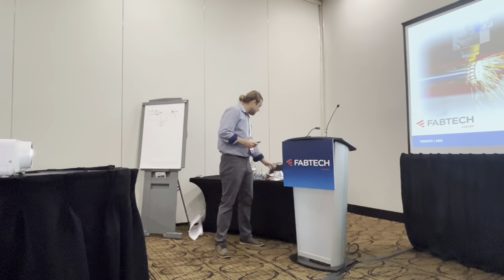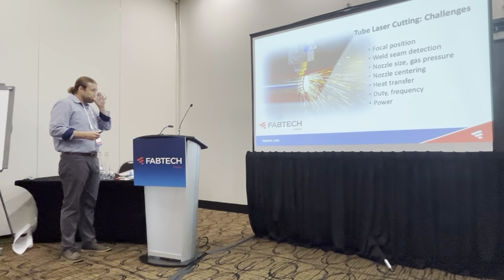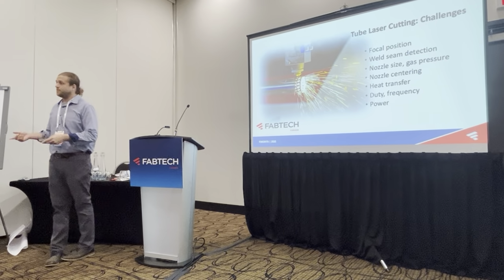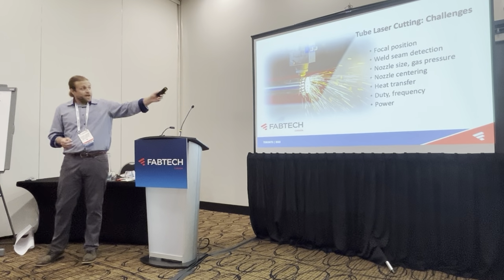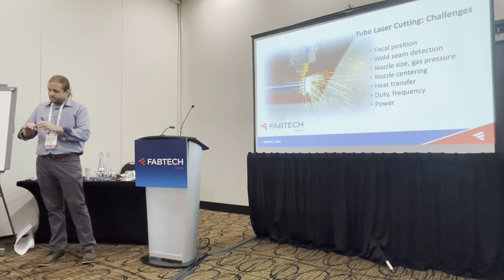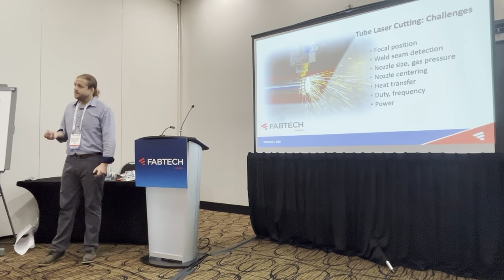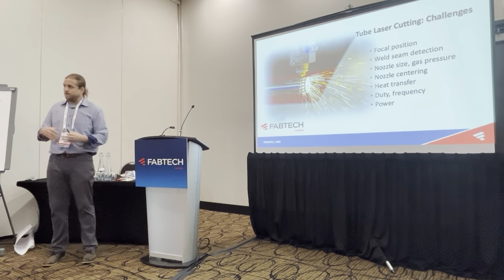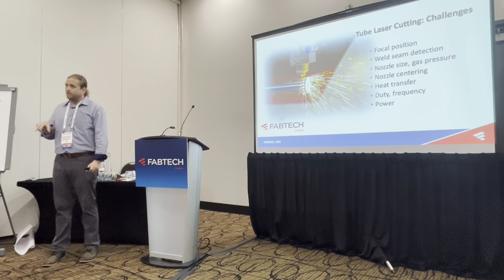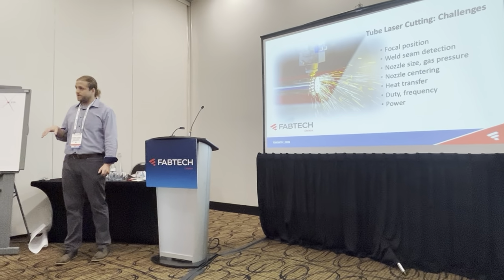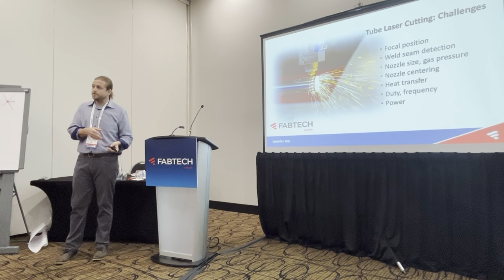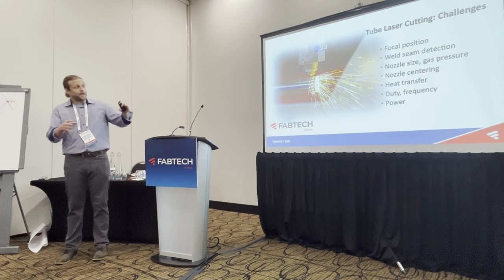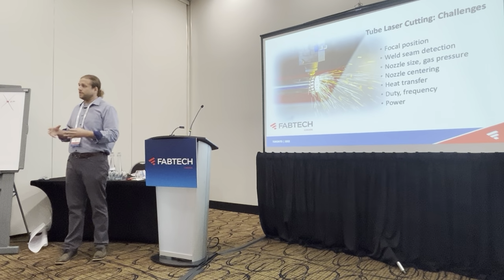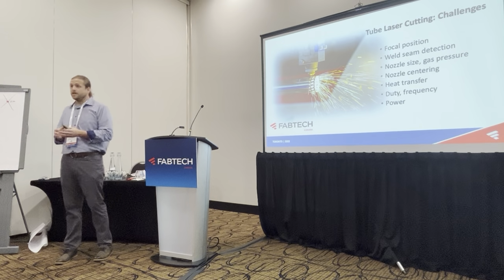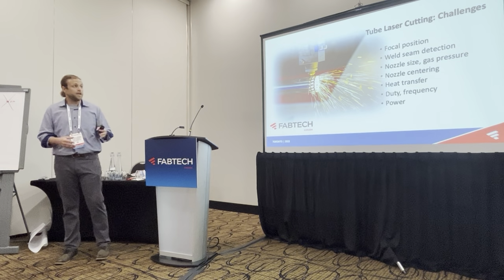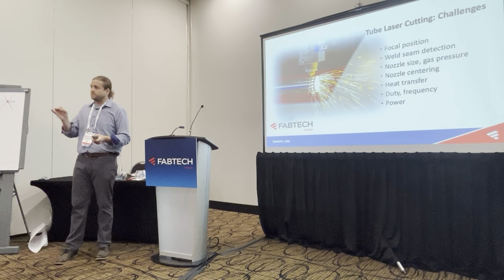Nozzle size, gas pressure play a huge role as well. Depending on the material, there's different nozzle sizes, and there's different nozzle sizes from oxygen to nitrogen as well. Your nozzle size on nitrogen is going to be, the porthole is going to be smaller for higher pressure, most likely, but obviously it changes depending on your material types. Nitrogen's always higher pressure, you're always playing in that 200 to 300 psi range, where oxygen, you're in the low hundreds to even under 100 psi. So that's where that gas pressure nozzle size plays a role. Oxygen, you're going to have lower pressure, different nozzle sizes. Nitrogen, you're going to have really high pressure and different nozzle sizes as well. And depending on material thickness type, that nozzle size changes.